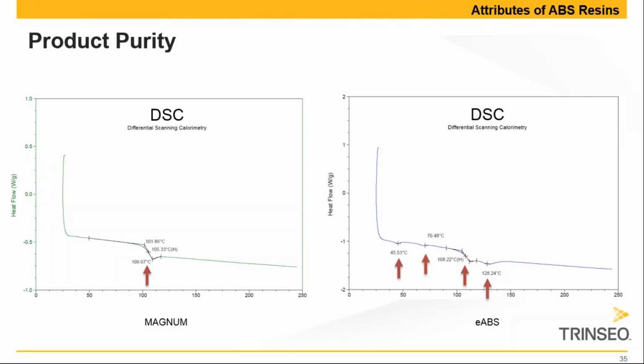If we move to the right side of the slide, we see the DSC experiment on the emulsion ABS. And indeed, at about the same temperature, around 105 degrees, you also see a changeover. This is the changeover of SAN. But in addition to that, there are 3 other changeovers, around 45 degrees, 70 degrees, and 128 degrees. These are changeovers of impurities present in the ABS.